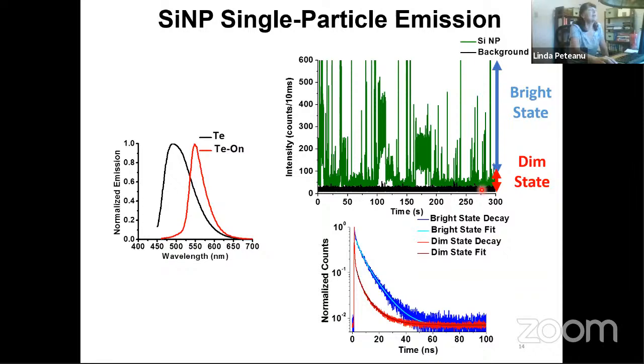So if we separate out, by using intensity thresholding, the bright state from the dark state, we see that they have different emission decay dynamics. The bright state decays with the same dynamics that you get for the system in solution phase. The dim state has a faster decay component. So it appears that it's possibly decaying by a non-radiative effect, which is why it shows less emission.